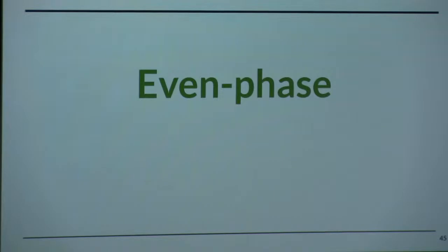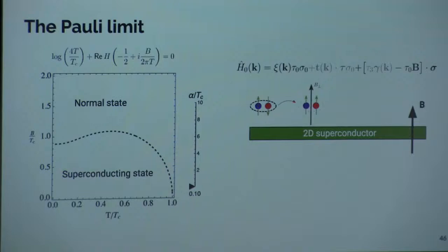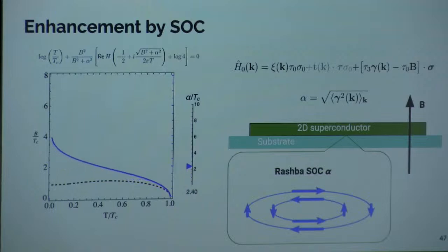Let us discuss the properties of the even phase. For this, I begin with a 2D superconductor, apply a magnetic field along the z direction. Here I assume that there is no orbital effect, and I also assume that the transitions are of the continuous type. If I now add a substrate, and here I'm adding a substrate just for didactic reasons, but in CeRh2As2, this happens intrinsically because of the crystal fields.